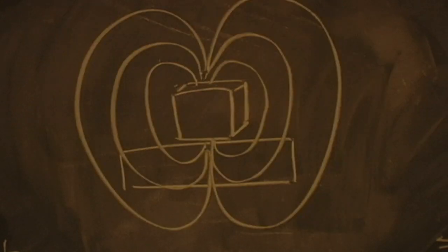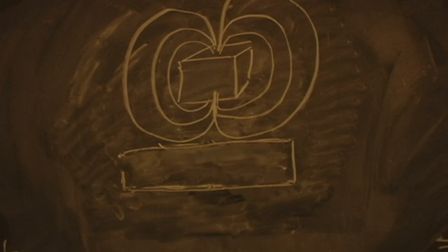If superconductors were to just exhibit zero resistivity, then we would not have seen what we saw. The magnet would not have levitated because YBCO was exposed to its magnetic field before it transitioned. It would want to maintain those field lines passing through it. The magnet levitates due to the Meissner effect. Upon transitioning into its superconducting phase, the YBCO expels all magnetic fields so that the interior has practically no magnetic field lines passing through. The Meissner effect is a property of thermal equilibrium, and it follows from the London equations.